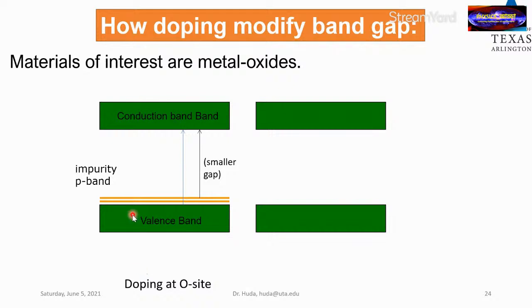If we dope nitrogen, as I just showed on the last slide, at the oxygen place, what it does is that it places those impurity nitrogen p bands above the original valence band. Because of the placing of this nitrogen p band above the valence band, the effective band gap is now smaller than the previous one. The previous one was from the green to green. Now we have a gap from the orange to the green. It's somewhat smaller.